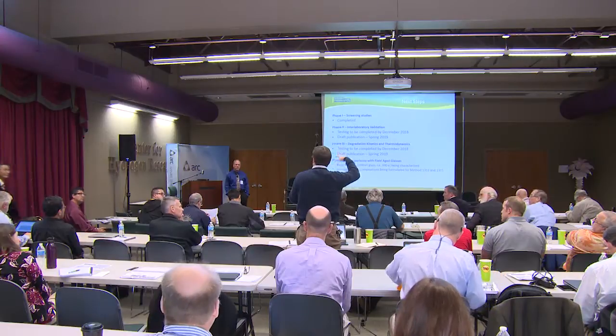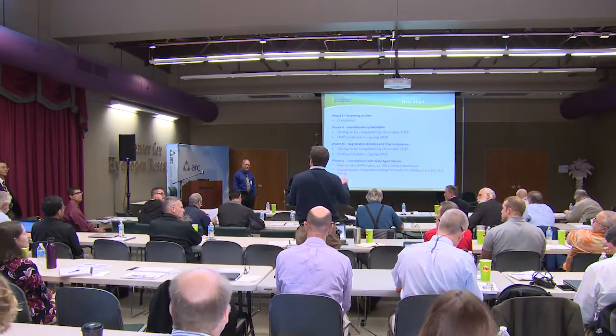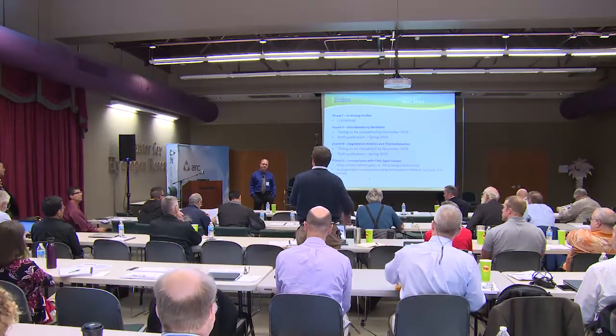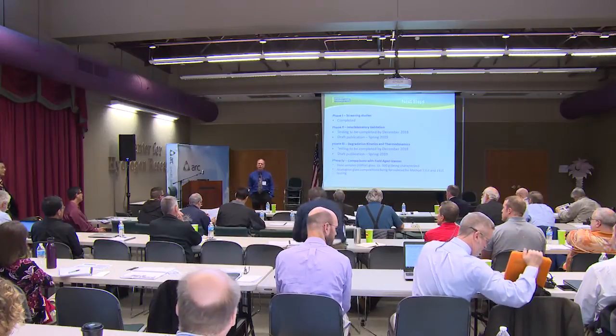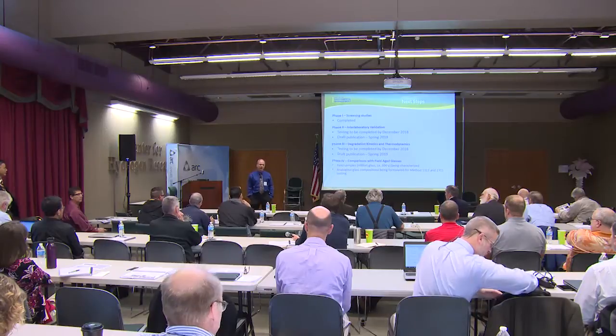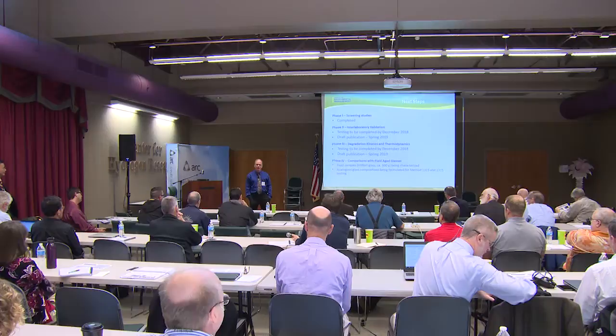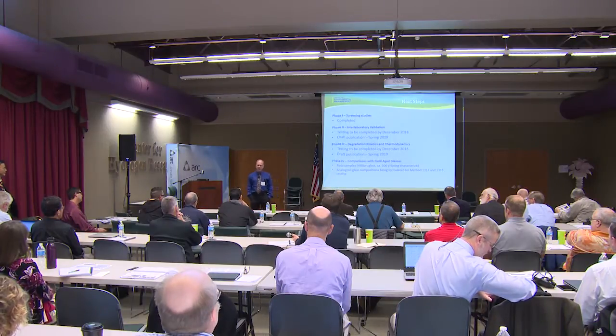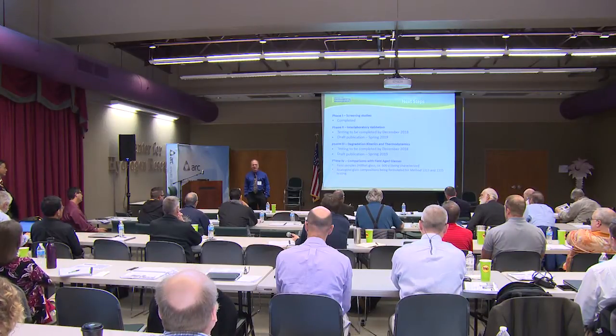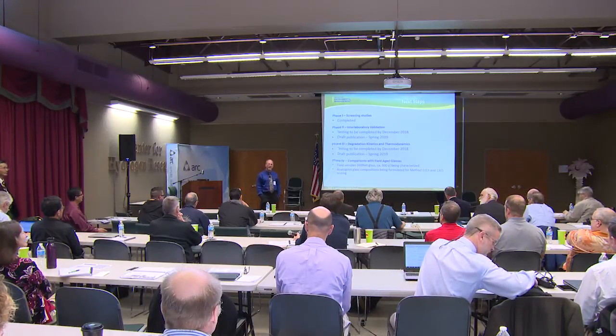Thanks for this. You mentioned reprecipitation of the iron. Do you think it is enough mass to impact the diffusion rate, or is it small, with other ions coming out? I don't think so, but what we're going to be doing is some very careful surface characterization to see what the distribution would be post-leaching of the longer time frames on the test coupons. There are different characteristics that we can do to look at the changes in the surface, and that's certainly going to be a question, though. I suspect not, but that's yet to be seen.